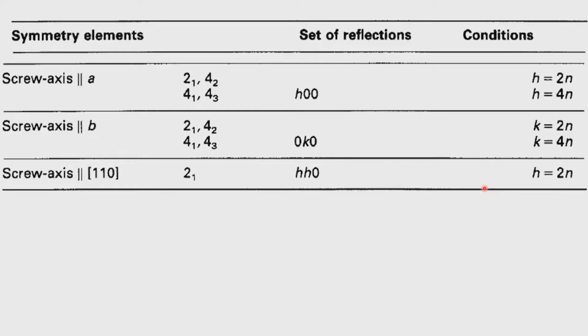So essentially we have now covered all the symmetry elements which will have translational components. The centering information that is associated with the lattice will also give half additions and so on, and therefore we have these systematic absences. We have systematic absences due to the glide planes. We also have systematic absences due to screw axis. So these translation components which are present only in crystals, that is a very important point to remember. These systematic absences are present only in crystals and they affect only diffraction, and therefore it allows for a unique determination in most cases of the space group.